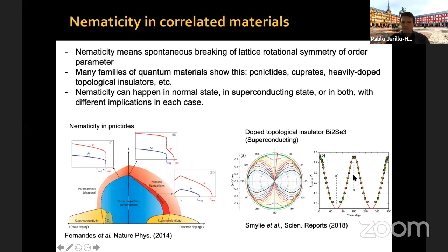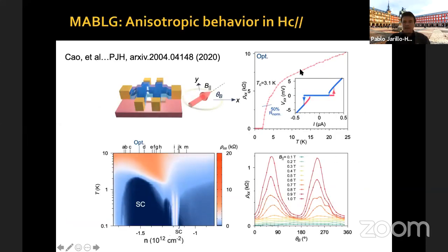So as you rotate the angle, you see this twofold in the critical temperature or in the resistivity. So this is a pretty high TC sample, and by high TC, I mean relative to magic angle graphene superconducting TCs, okay? 3 Kelvin at 50% normal state resistance. You can see beautiful superconducting curves with very nice switching currents. And of course, this superconductivity is dependent on the carrier density, okay? This is a log scale. This is one of those samples, by the way, which exhibits a depletion of TC around this point, which in log scale now is very clear.